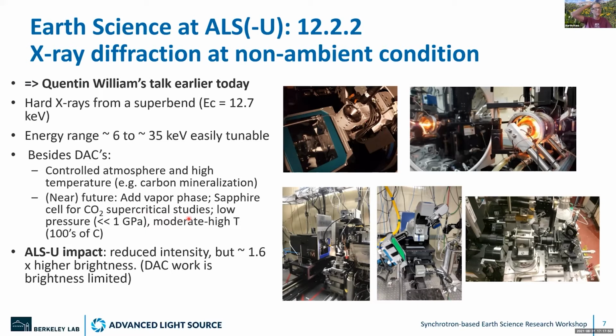The impact of the ALS-U upgrade on the operation of beamline 12.2.2 is that it will reduce the intensity somewhat, but all the diamond anvil cell work is brightness limited because we refocus the source onto the small sample volume, and we gain brightness by about a factor of 1.6. Not exactly orders of magnitude, but plenty to satisfy a lot of demand, which does not necessarily need the absolute highest brightness.